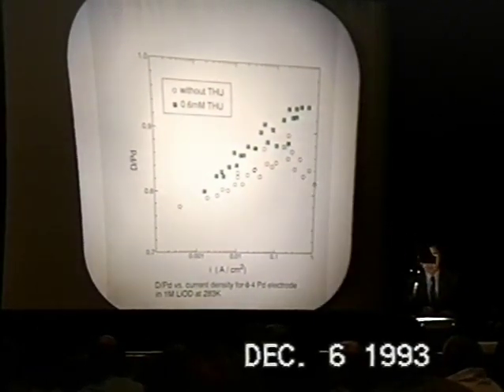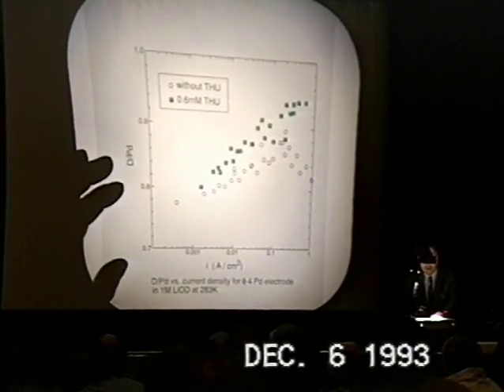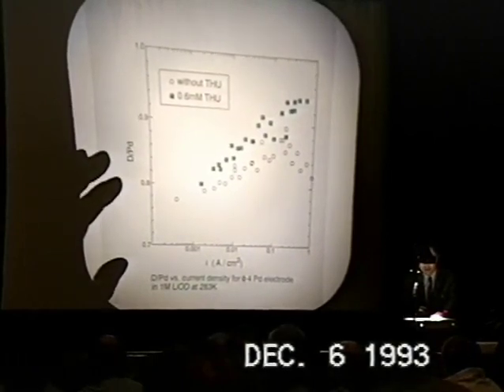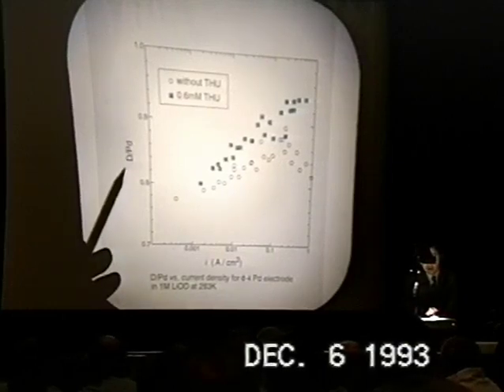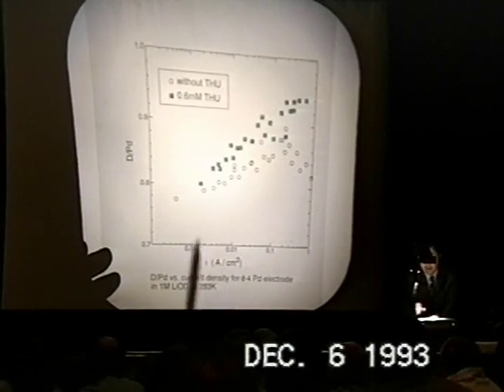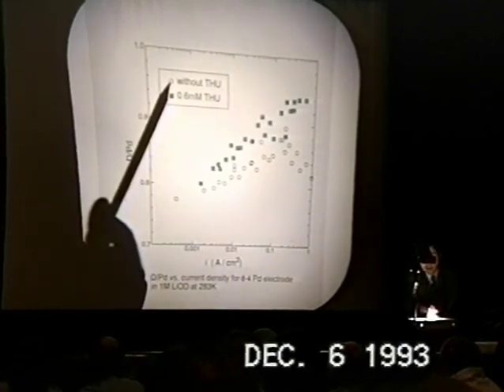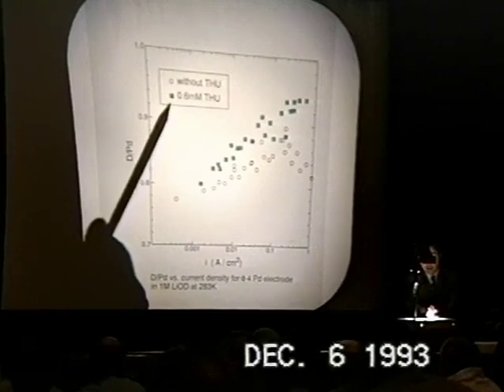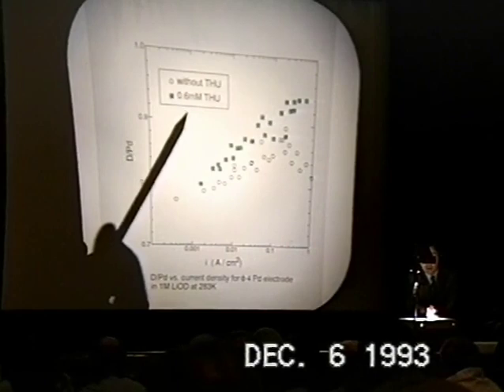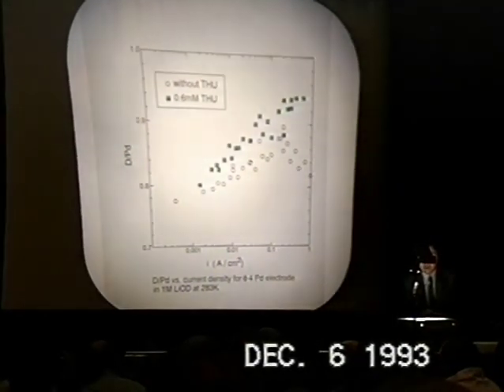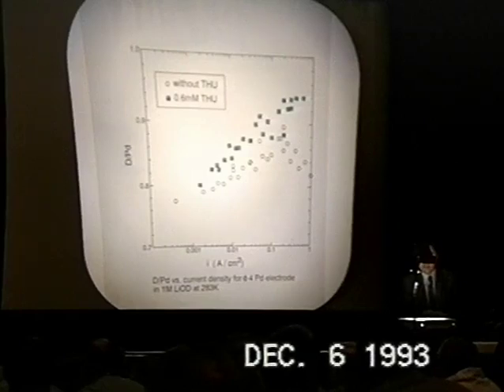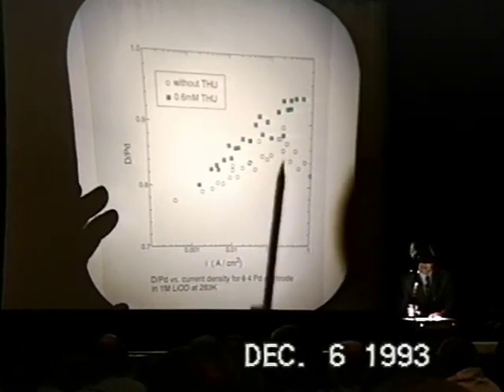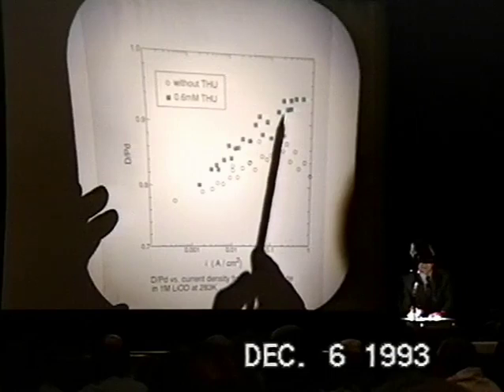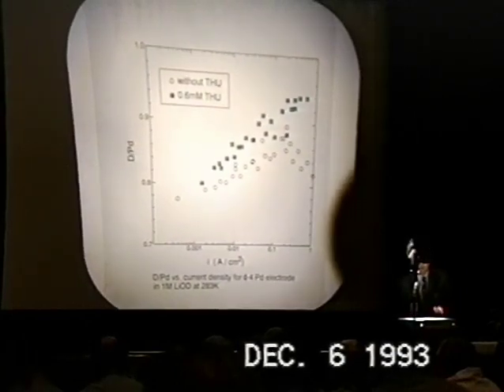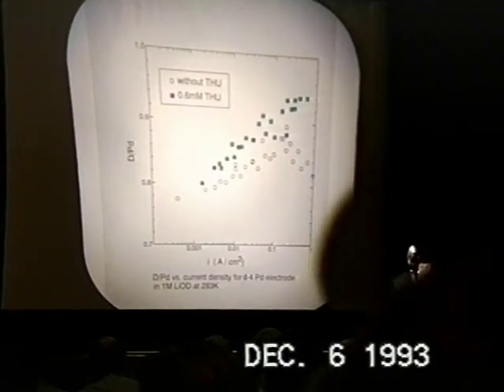Then I'm showing the effect of thiourea for the 1 molar LiOD system. I'm plotting the deuterium loading ratio as a function of cathode current density for pure 1 molar LiOD and 1 molar LiOD containing 0.6 millimolar thiourea. If you look at this data, it is very easy to see the effect of thiourea to increase the deuterium loading ratio substantially in this region. So we have nearly 0.93 or 0.94 for the maximum deuterium loading ratio in the presence of thiourea.